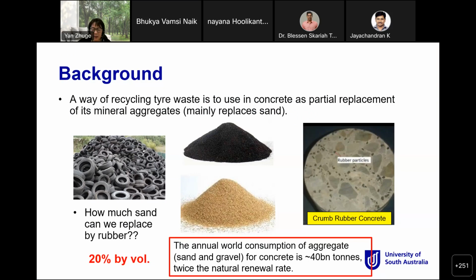rubber. So that's about 70 kilograms of rubber per cubic meter that could be used in concrete. Based on these calculations, about 1.68 million tons of tires could be recycled. So there is a big potential for the construction market to use recycled tires. This diagram shows the tire after shredding that we got from our industry partners, and this is normal sand, and that is crumb rubber concrete we made from these tires.